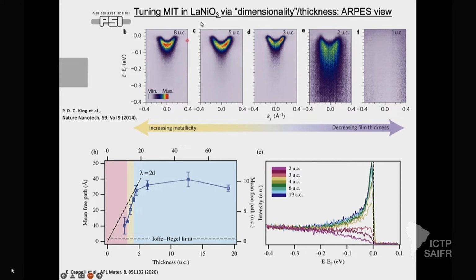So, if you are looking at lanthanum nickelate, which should be all the way metallic, this is what we call the electron pocket at the gamma point. For 8 unit cell it is well defined, which means that the system is very metallic, with a very well formed quasi-particle peak. Then you go to lower thicknesses, there is a bit of a subtle change at 3 unit cell. Okay, the system is still almost the same metallic, and then you go to 2 unit cell, there is a very drastic change, so that the incoherent parts start to pop up, and the quasi-particle peak seems to be going down, and then the 1 unit cell system is gone. There is no metallic state at the Fermi level.